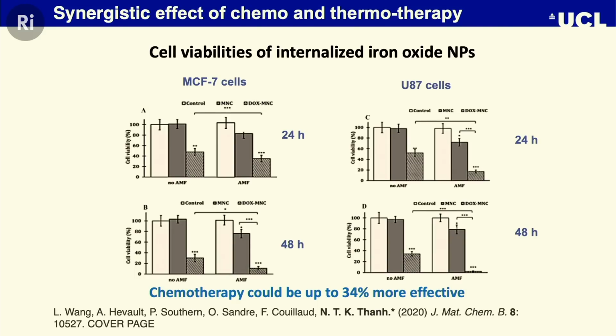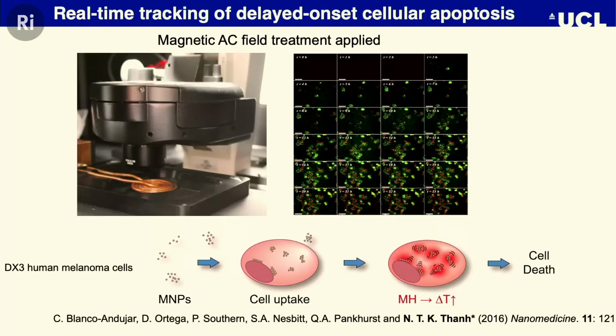And you can see the bars, you only need to look at one of them. This one is the control in the beginning, and this one is the magnetic nanoparticle, and the magnetic nanoparticle with the drug. And you can see that the bars are going lower. That is the cell viability. So you have a synergistic effect, which means the sum is larger than its parts, so you could have a better effect. You can use a lower dose of chemotherapy, helping with the side effects, and also a lower dose of magnetic nanoparticle for the treatment.